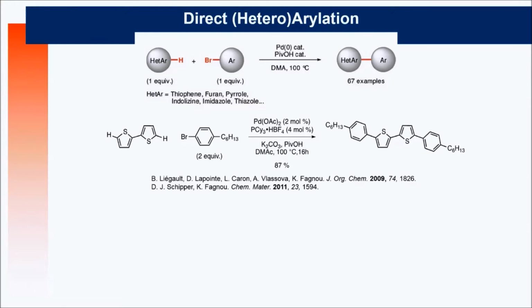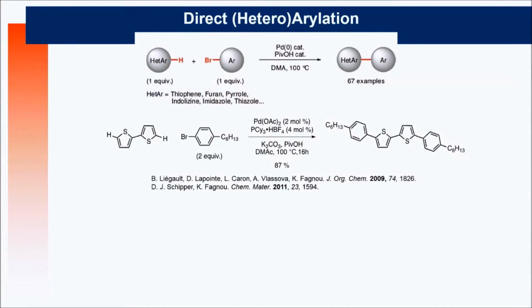And that's the PhD work of Direct Heteroarylation, with the late Keith Fagnou. And they show that it's possible to make reaction with CH bonds. And for us, I was not aware, it was impossible. Based on palladium, I mean, the catalyst is not so fancy. It's not so complicated. So they made aromatic compounds here. The yield is 87. And it's exactly a conjugated oligomers here.